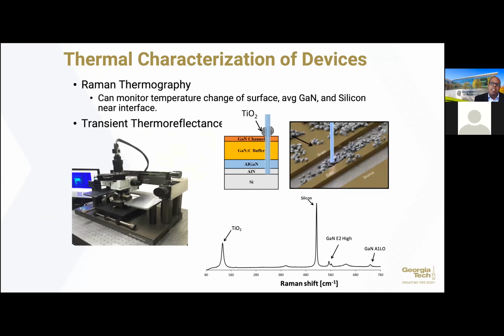We're going to use Raman spectroscopy. Here's a nice technique that you can use to measure temperature. How does this actually work? When I use Raman spectroscopy, I have a laser that can go through the material because it's transparent to my laser wavelength. I still get scattering where I get a peak for silicon. I can also see peaks for gallium nitride. I see two peaks here. And then I can also put nanoparticles on top, which are TiO2, which don't impact the electrical performance.